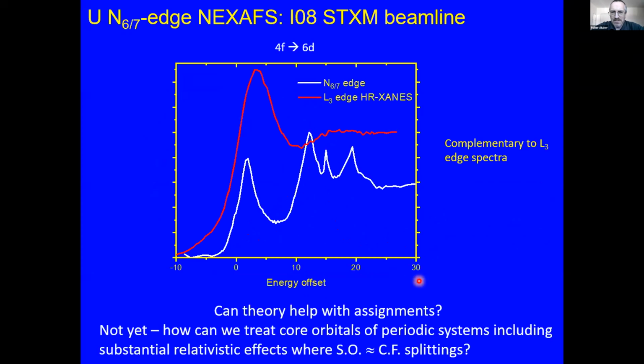So in certain circumstances, you think that this looks like it fits really well. However, we have problems with theory because it's really difficult to treat core orbitals of periodic systems which already have substantial relativistic effects, and spin orbit and crystal field splittings are about the same. But if we overlay our N6-7 and L3 edge spectra, you can see that they do seem to give us complementary data. And we think this is a really exciting use of STXM.